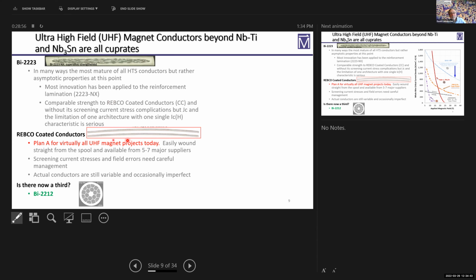So I would say, however, for high field magnets, it's not plan A. And plan A is rare earth barium copper oxide, where the rare earth may be yttrium. It may be yttrium mixed with gadolinium or something else. And what you do here, and I'll show you the architecture in a minute, but this is a real cross section. So you see, this is a tape. Previously, I was showing you round wires, and the tape aspect ratio is even greater here. So this is something that you would tend to wind as pancakes and stack the pancakes one on top of one another, which is, well, okay, but it's not, in fact, the most desirable way of making a high field, high quality solenoid. But this is a very interesting material.